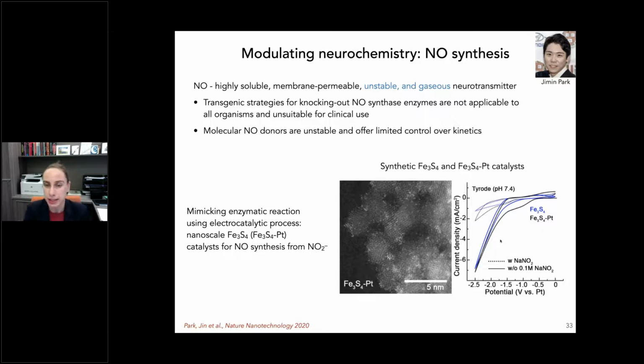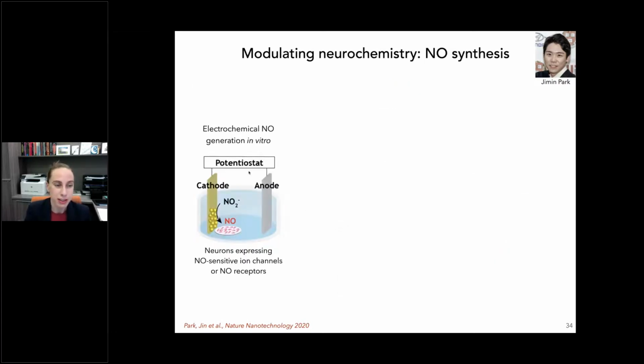But how do we test that, in fact, the nitric oxide synthesized in the electrocatalytic cell has biological activity? We take our electrocatalytic cell, which is about 5 centimeters or a couple of inches in diameter, and we then take the cells that we plate onto a little cover slip, and we put them next to the cathode of our electrocatalytic cell, and then we drive the synthesis of nitric oxide. We can then test this